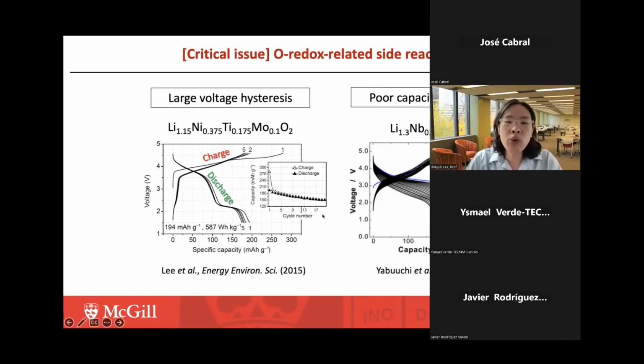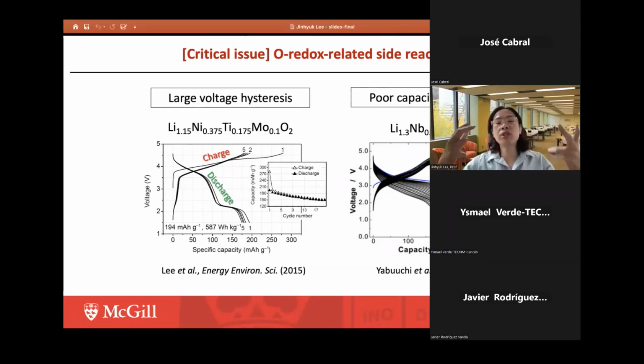For example, here I'm showing you the voltage profiles of two different DRX compounds, which are lithium nickel titanium oxide and lithium manganese niobium oxide. First of all, if you look at the left voltage profile, we can see that the charging and discharging curves look very different, right? They're asymmetric. So this shows that there is some intrinsic voltage hysteresis coming from some weird redox mechanism. Also, if you look at the right voltage profile, we can see that although this lithium manganese niobium oxide delivers very high capacity, up to 300 milliampere hours per gram in the first cycle, this capacity quickly drops to less than 170 milliampere hours per gram after only 20 cycles, which basically shows poor capacity retention.